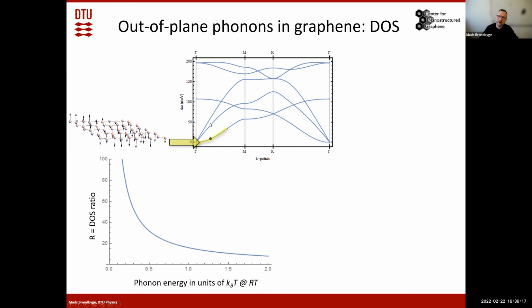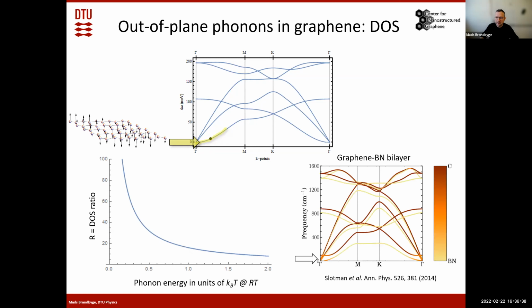Whereas if you look at the other acoustic branches, the density of states goes to 0. So that means that even at room temperature in graphene, if you look at the ratio of density of states, you have maybe a factor of more than 10 of out-of-plane modes than in-plane modes. So they are in principle very dominating.